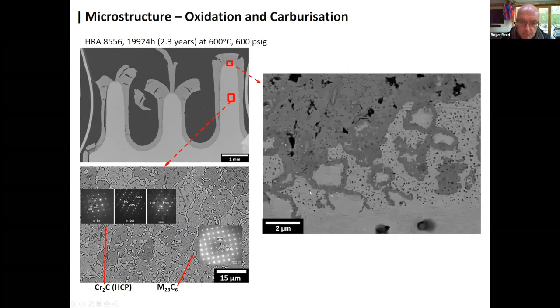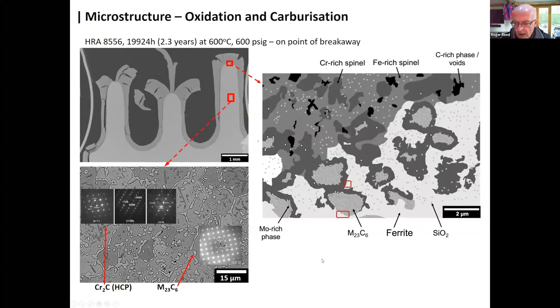And if you look at the microstructure close to the interface between the oxide and the metal, then there is a very interesting microstructure. You can see that the substrate is heavily carburized, so these are large M23C6 carbides which have formed, and then around this is a spinel type iron and chromium rich oxide which forms, because of course the carbides then are becoming progressively oxidized over time. So this is an interpretation of that microstructure. You have here the carbides.